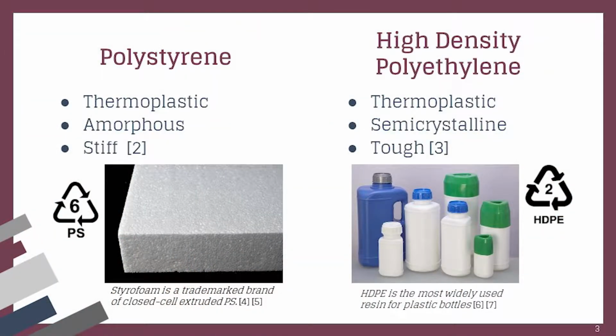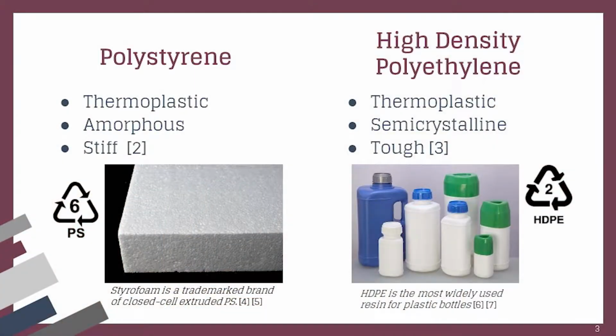So the two plastic polymers that we will be using were polystyrene and high-density polyethylene. Polystyrene is a thermoplastic with an amorphous structure, and despite this amorphousness, it's still relatively very stiff. The other material that we used was high-density polyethylene, which is also thermoplastic, but instead it's semi-crystalline and it has a tough structure. The abbreviation we'll be referring to for polystyrene is PS, and the abbreviation for high-density polyethylene is HDPE.